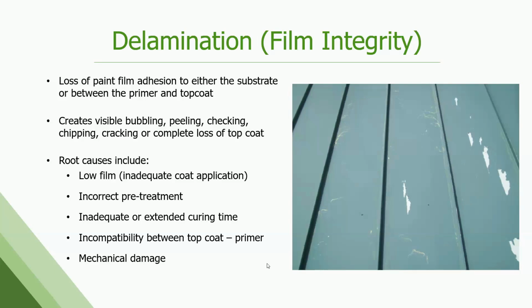Low film is often a cause of this. You don't have enough film on there, so that UV is penetrating and breaking down those bonds. The paint comes off. Maybe the pre-treatment underneath wasn't good. Maybe the substrate wasn't cleaned well before you painted it. Maybe it wasn't cured right. This is fun. If you under-cure it, or if you over-cure it, you could have the same mode of failure in the field. That's a fun one. Incompatibility between top coat and primer.